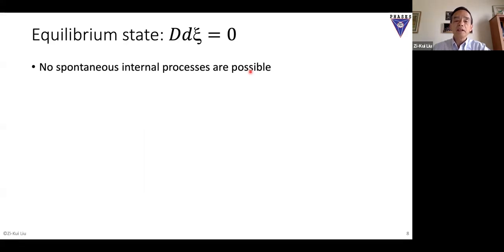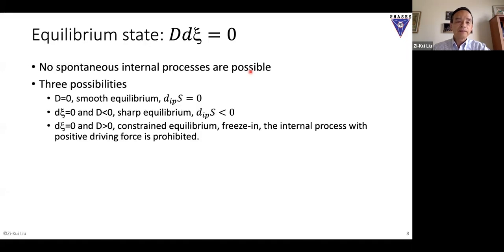No spontaneous internal processes are possible. But it turned out that because there are two variables here, there are three combinations. The first combination is D equals 0. If D equals 0, you can do derivatives, basically. So we call it smooth equilibrium because you can calculate the derivatives. Another one is sharp equilibrium, because D is negative, but dξ is equal to 0 because nothing happens, right? There's no driving force. We call it sharp equilibrium. For example, you burn a wood, it can completely burn, right? Nothing left. It's a sharp equilibrium because all becomes carbon dioxide.